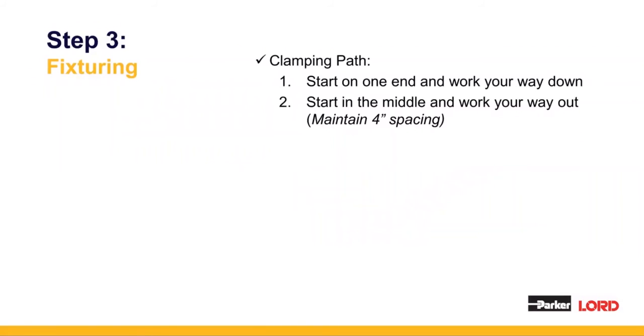Once you have your parts laid out the way that you want them, it's time for clamping, or fixturing, as we call step 3. Your parts should be weighted with even pressure until handling strength is reached. You also want to follow one of the 2 recommended paths for proper clamping. You can do this either by starting on one end and working your way down, or you can start in the middle and work your way out, making sure that you maintain about a 4-inch spacing in between each clamp. The path you choose will depend on the size and the shape of your parts, but this is really your preference. What you don't want to do is start on either end and then work your way towards the middle.